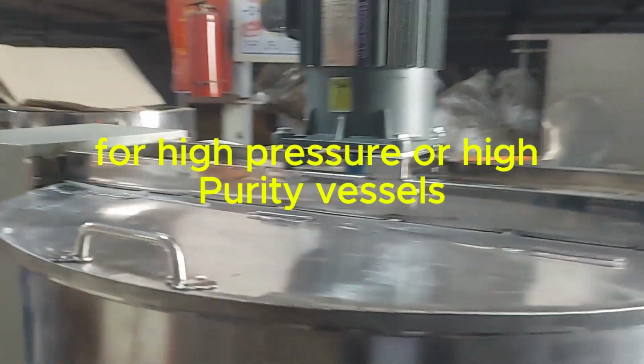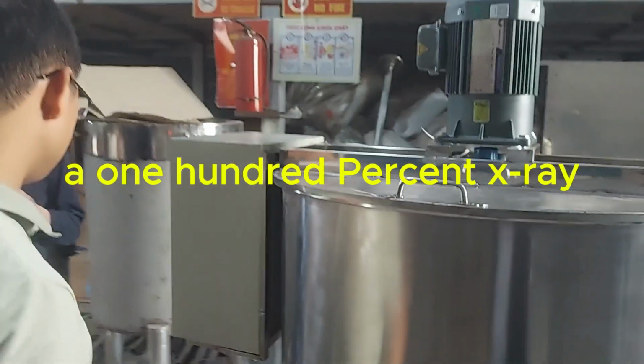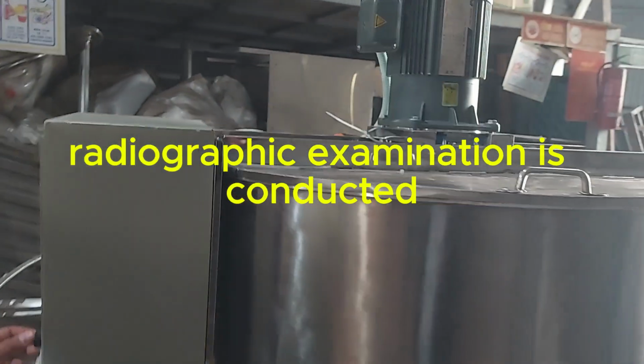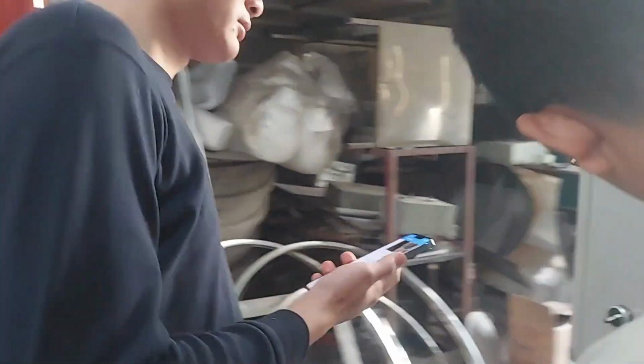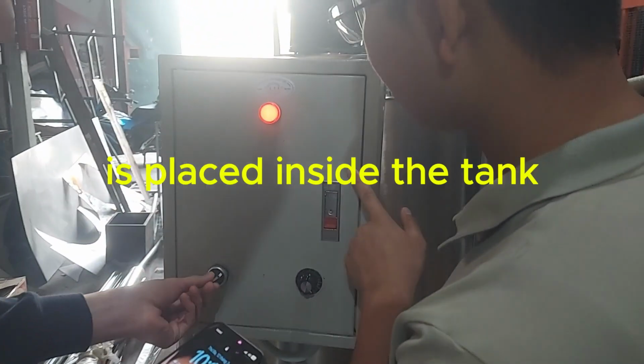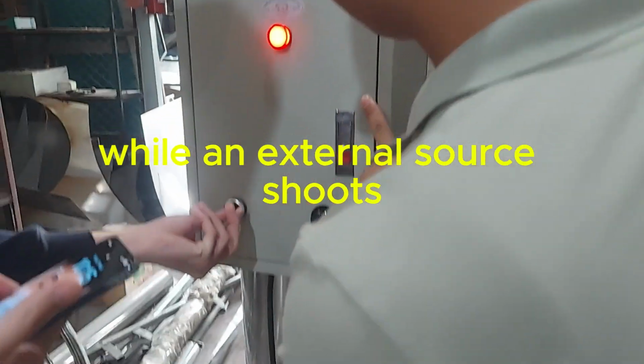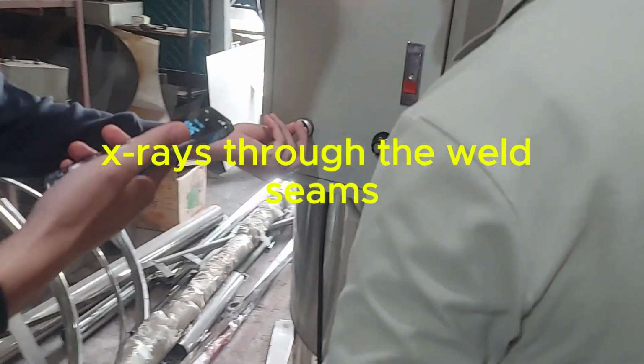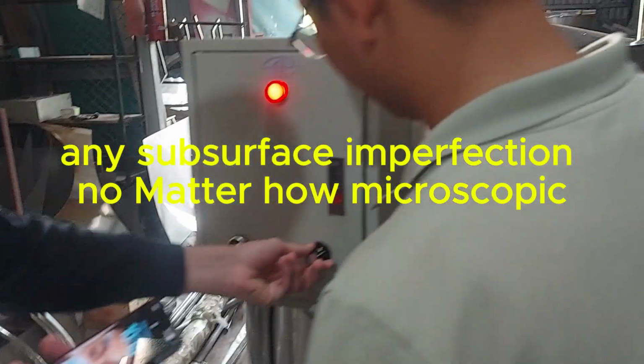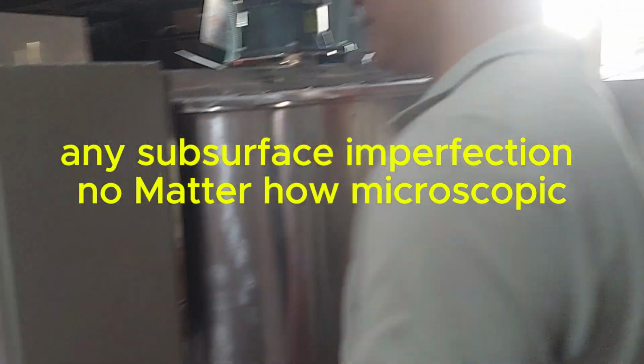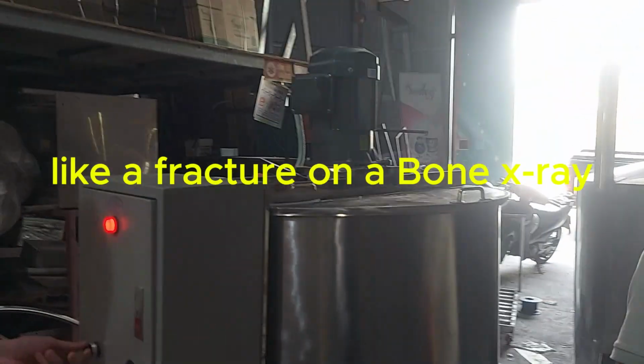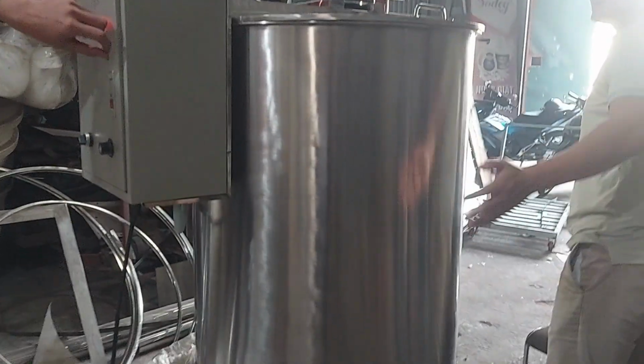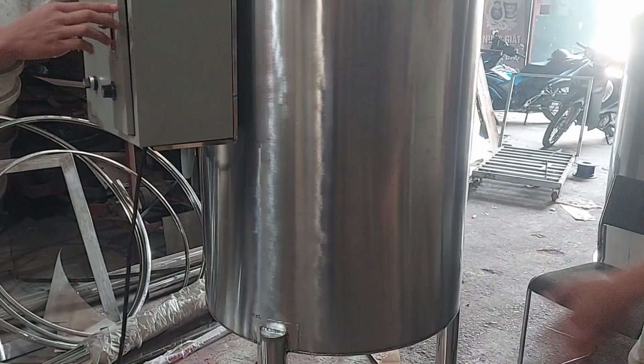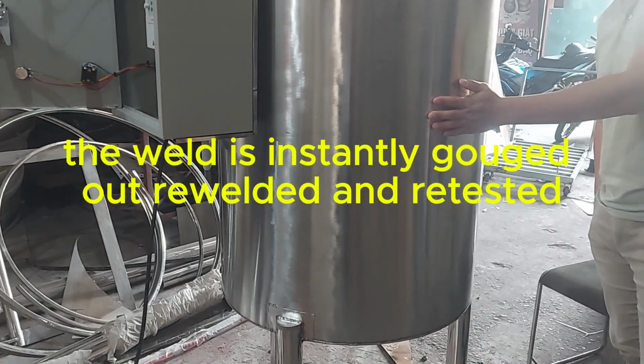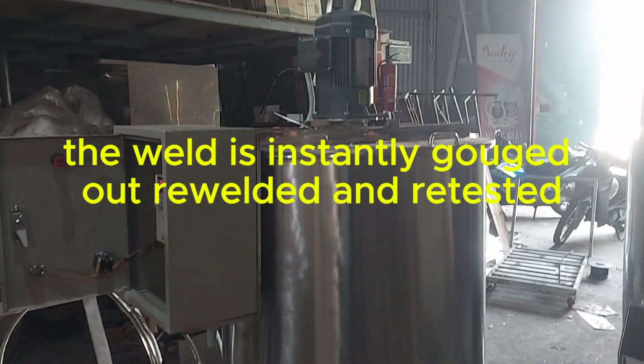For high-pressure or high-purity vessels, a 100% X-ray radiographic examination is conducted. Industrial radiation film is placed inside the tank while an external source shoots X-rays through the weld seams. Any subsurface imperfection, no matter how microscopic, will appear on the film like a fracture on a bone X-ray. If even a single defect is found, the weld is instantly gouged out, re-welded, and retested.